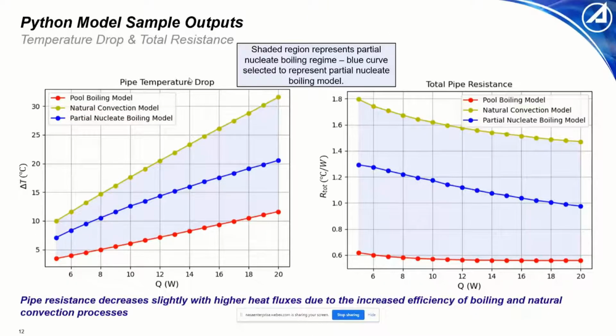Here are a couple pictures of our sample outputs. As I said before, these correspond to 3 different solutions. For every heat input value, in this case, the code was run for a sample geometry from 5 to 20 watts. At 5 watts, all the way through 20, there are 3 different temperature drop solutions. Again, those 3 solutions only differ in that the node network is changed slightly by changing the evaporator resistance from nucleate pool boiling to partial nucleate boiling to natural convection.